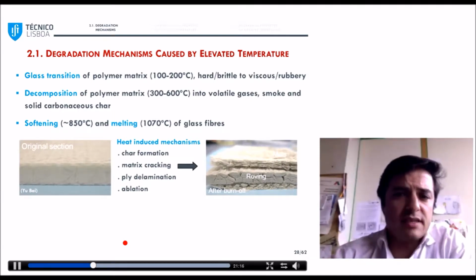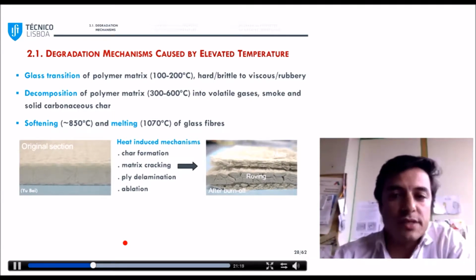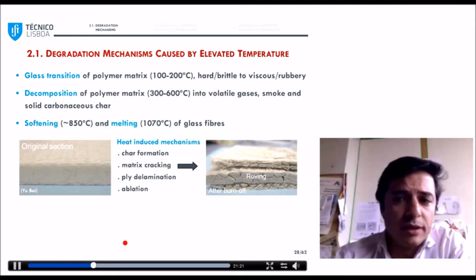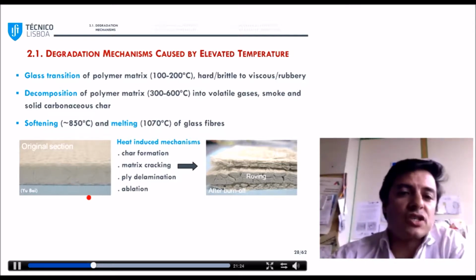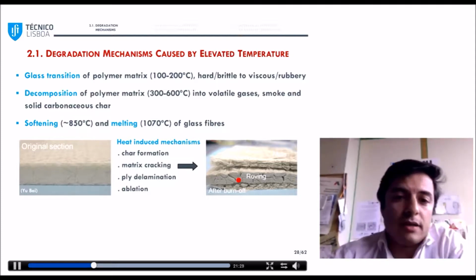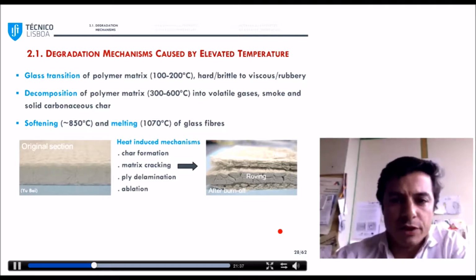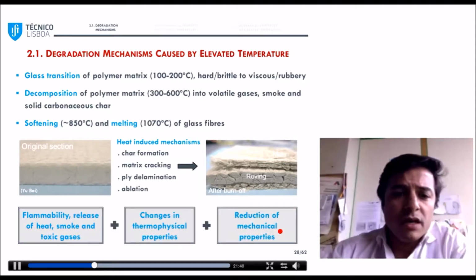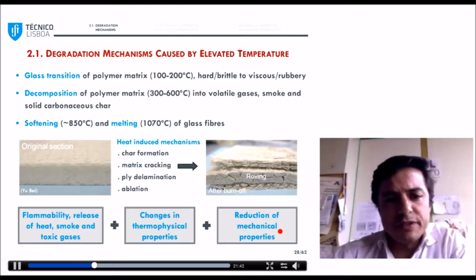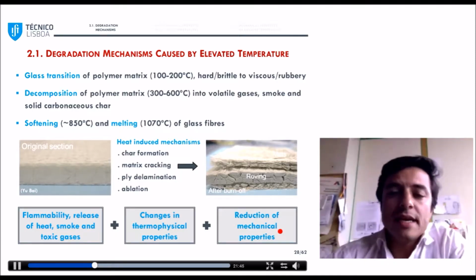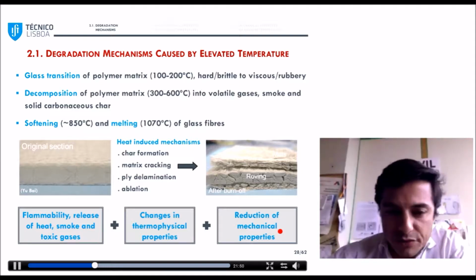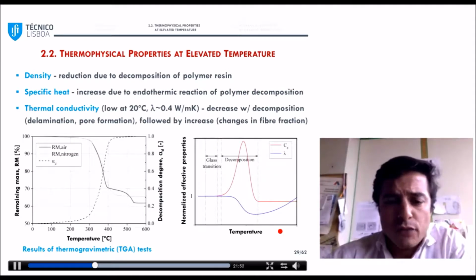And therefore, as a consequence, there are a set of heat-induced damage mechanisms in the material. So this is the original section, and after burn-off, we will have char formation, matrix cracking, delamination, and eventually ablation with layers of material falling away. So in addition to the release of heat, smoke, and toxic gases, there are also changes in the thermophysical and mechanical properties of the material.